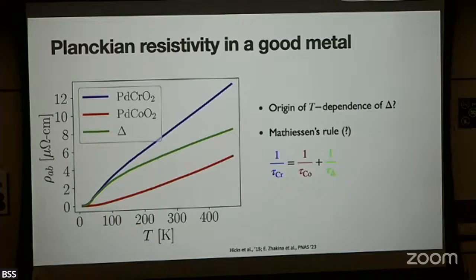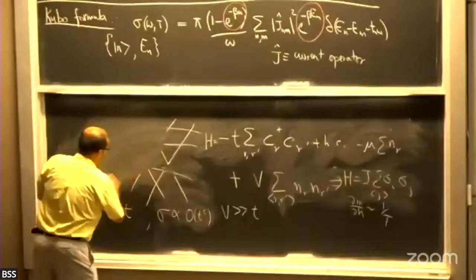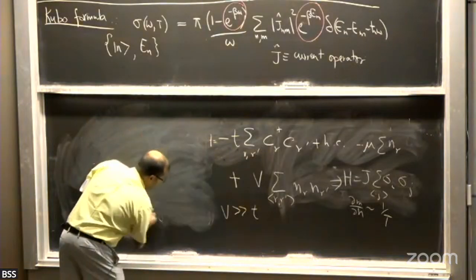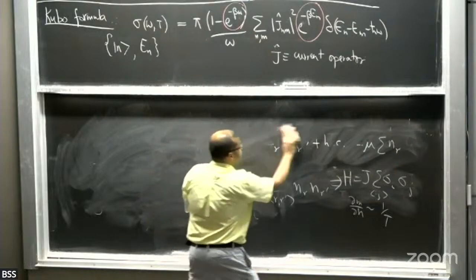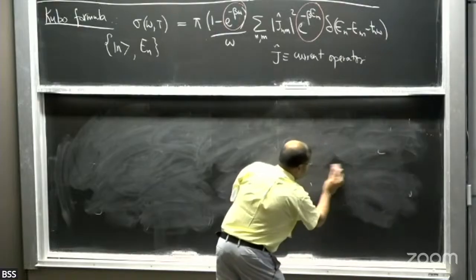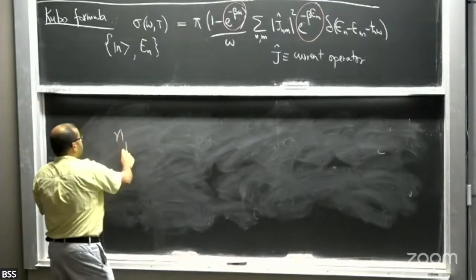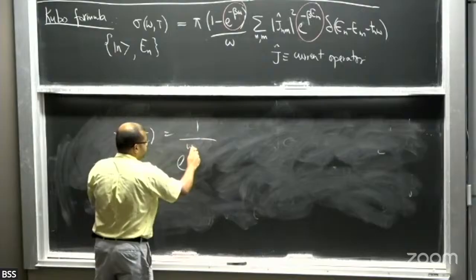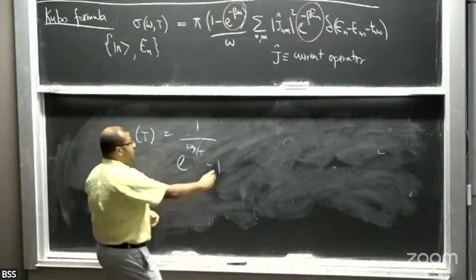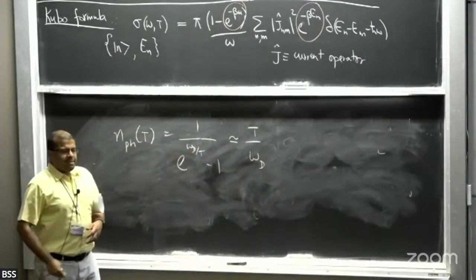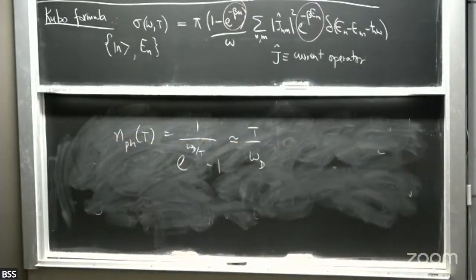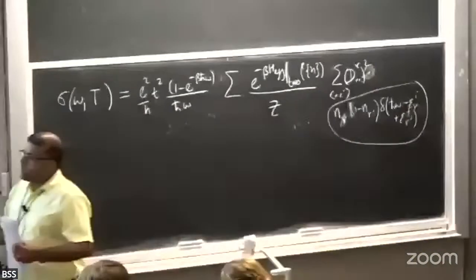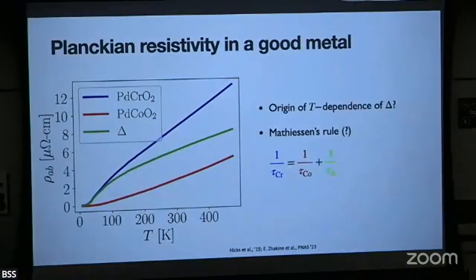Scattering off of phonons is very, very different from scattering off of local moments. And as I emphasized at the beginning, phonons have a completely unbounded spectrum. Their occupation is just determined by the Bose-Einstein distribution. If you're at temperatures well above the Debye frequency, the number of phonons as a function of T goes as, right? So if you take the high temperature limit, this basically becomes T over omega Debye. Okay, that's not how spins work. These are local moments. They have a bounded Hilbert space. There's no sense in which you can create as many spin excitations in that paramagnetic state. So in the high temperature limit, as the electrons are scattered by the normally fluctuating paramagnet, the temperature dependence of the scattering rate is going to saturate. So that can't be responsible for this enhanced T-linear resistivity in palladium chromium oxide.